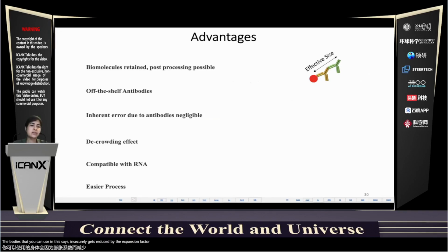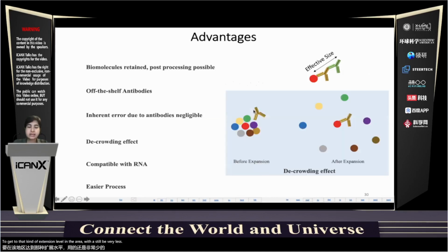So if the size of the antibodies, primary and secondary together, is around 30 nanometers, then by expanding about 20-fold, the effective size becomes around 1.5 nanometers. So that means it is possible in the future to get to that kind of expansion level, and the error will still be very little. Another novel effect of this technology is the decrowding effect.